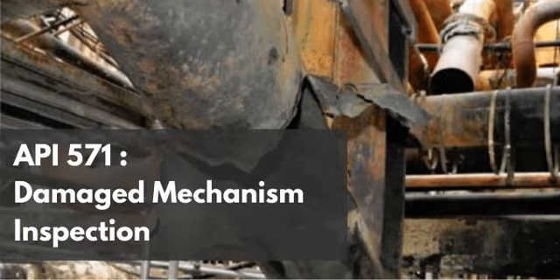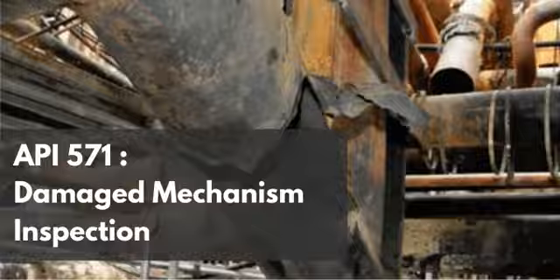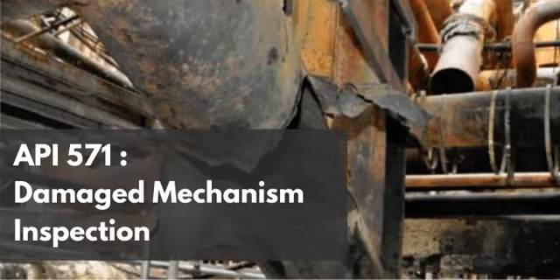Often, they have to push the furnace well beyond its normal, safe operating temperature just to get the dense coke to ignite and clear out of the system. And there's the trap. That is the trap. If that massive temperature spike pushes the actual metal of the tube significantly over that 1100-degree Fahrenheit threshold, consider what is happening at the microscopic level. The atomic doors swing wide open.